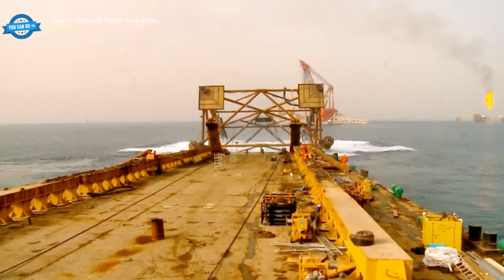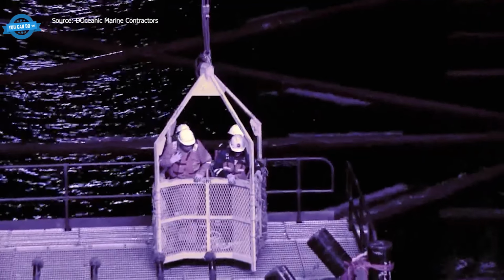A heavy derrick vessel transports and installs giant offshore steel structures weighing thousands of tons. What looks slow from a distance is actually a tightly calculated sequence where balance, sea motion, and lifting stress are monitored constantly. In this operation, a 2,000-ton jacket slides directly from the barge into the water before a separate 1,500-ton topside is lifted into position. The vessel's main crane can handle up to 4,400 metric tons, allowing massive offshore assemblies to be positioned with controlled precision, even in difficult marine conditions. By this stage, even a small alignment error can delay an offshore project worth millions.